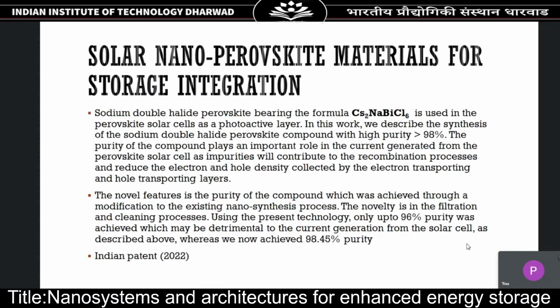And I also worked on solar nano perovskite materials for storage integration. So one of the compounds we chose was cesium sodium bismuth. This is used in perovskite solar cells as a photoactive layer. And we have been able to synthesize the perovskite compound with high purity, which is more than 98%. So purity is very important in the perovskite because for the current generated from the solar cell, if you have impurities, they will contribute to the recombination process, and that will reduce the electron and hole density, and effectively the cell will not perform as well. So we have changed some of the filtration and cleaning processes and improved the purity to 98.45%.